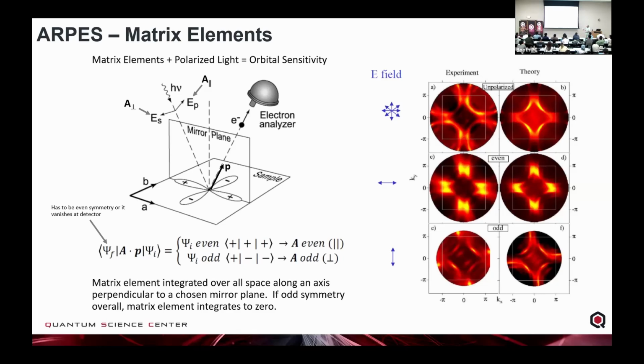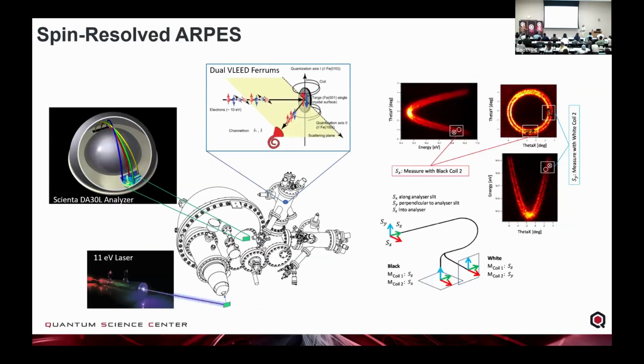If we have our A parallel to this mirror plane, then we're going to enhance the intensity. But if you rotate the sample 45 degrees, then it would be odd symmetry and we would suppress that. Then we would have to have a vector field perpendicular to that mirror plane in order to enhance that intensity. So now we get some orbital selectivity to understand the orbitals that are playing a role in a lot of the physics and the electronic properties that we see.